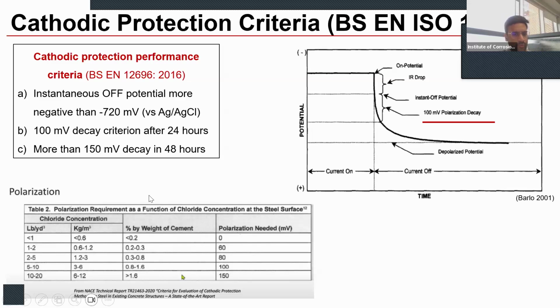Recently, NACE published this technical report, TR21463-2020, which specifies the polarization needed depending upon the chloride concentration in concrete. Supposedly if we have a higher chloride content, generally typically for concrete in the range of 0.8 to 1.6 or even lesser, 100 millivolt is required, similar to the protection criteria of BS 12696. However, unlike the BS criteria, it says that if the chloride concentration is lower, that means 0.6 to 1.2 or even lower, even a lower polarization can show that the system is working fine.